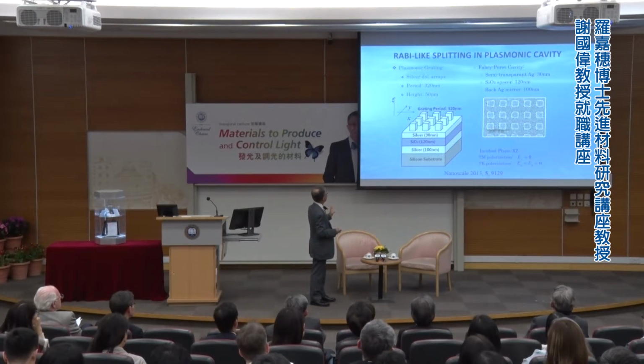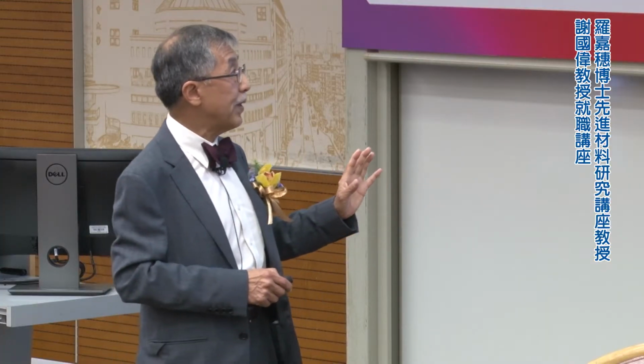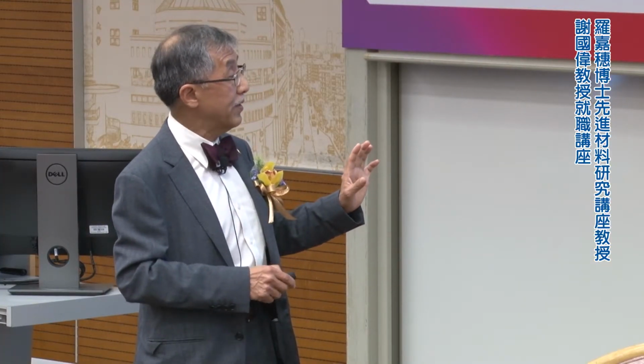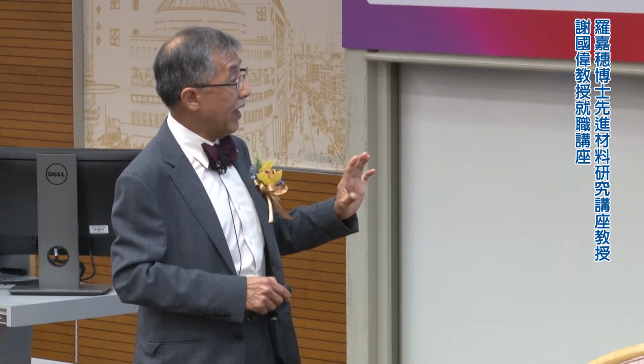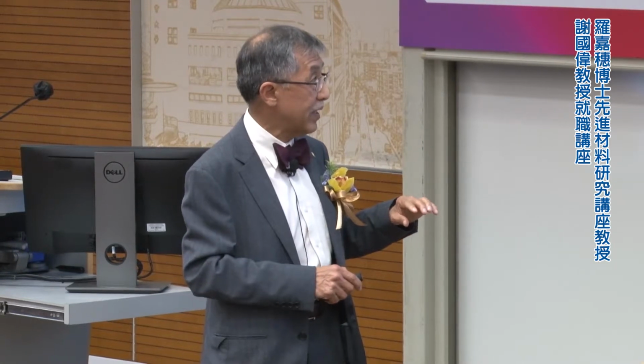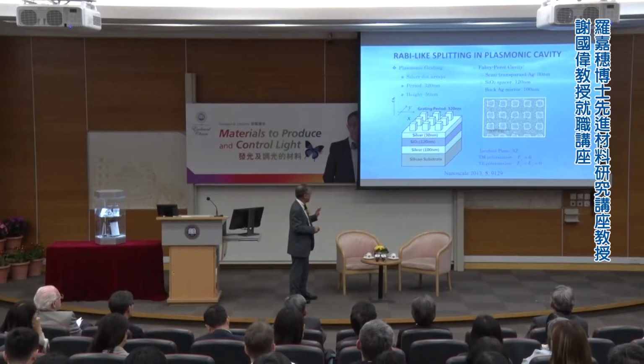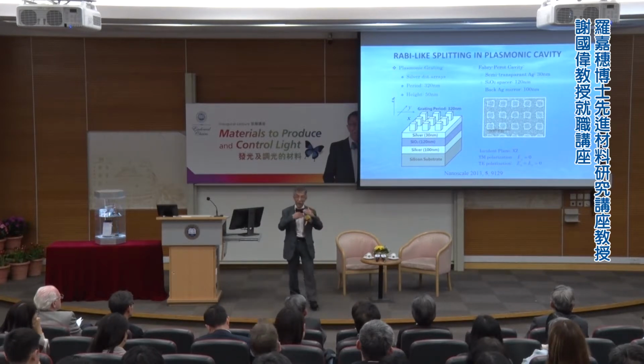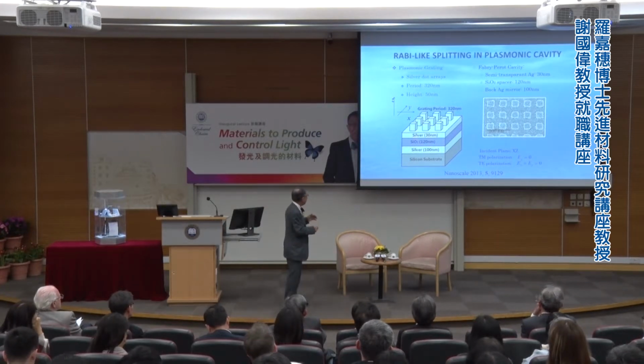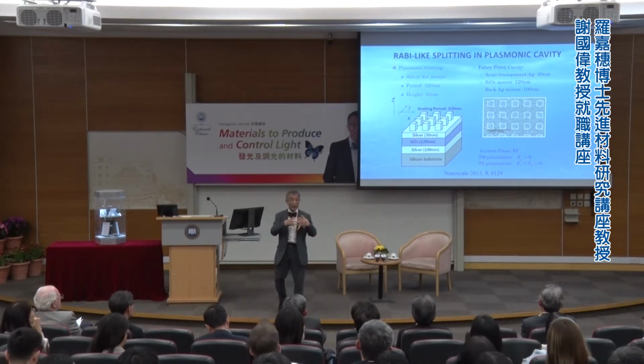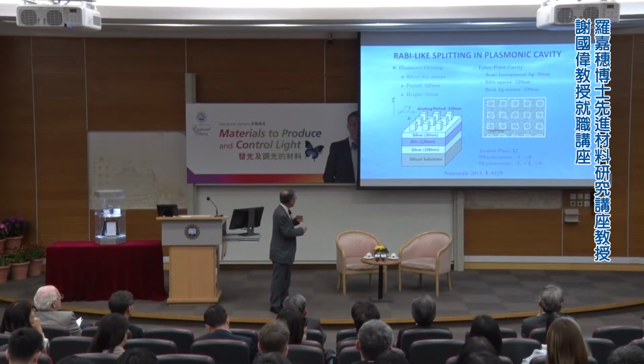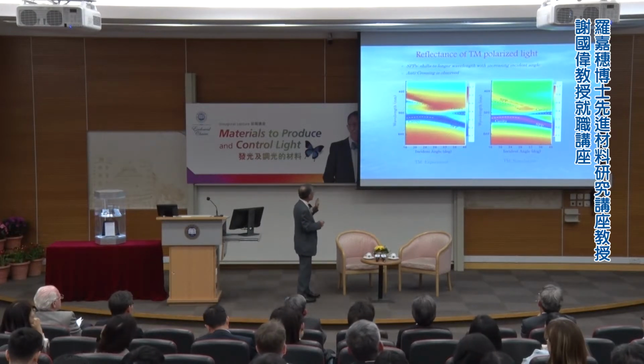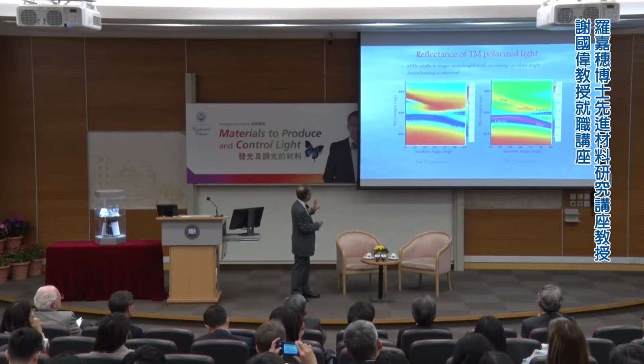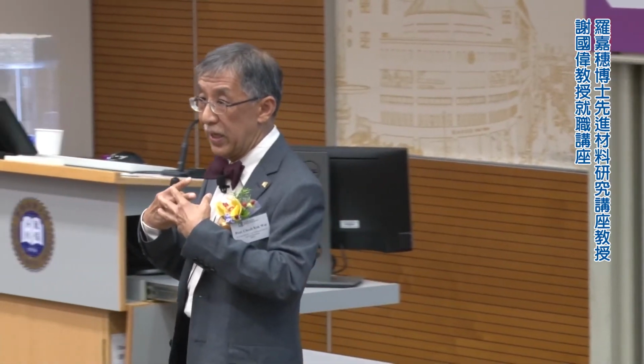I'll jump a little bit because of time. We have another structure here where we have silver. We have a matrix of silver there. Underneath that, we have what we call a microcavity. We have an insulator sitting between 2 layers of silver. We're creating what we call a standing wave inside the cavity, and that can couple to the plasma electrons inside there. By exciting this, the energy can transfer and they interact. What we have shown here is what we call the plasmon, we shortly call SPP. This is the cavity mode. They're broken up in the middle because they exchange energy. So it opens up a gap.